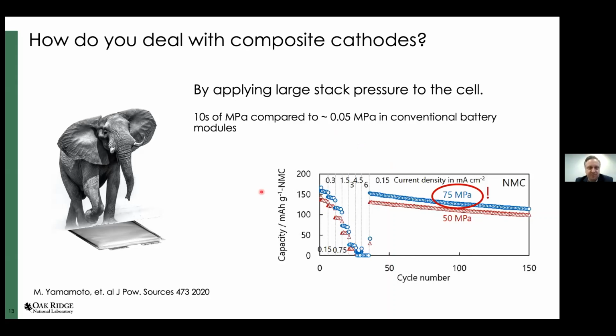Mark, I unmuted you in case you want to add anything. Yeah, no, I'm quite concerned about these pressures, and if you're scaling up and trying to make large pieces, if you have any kind of flaw, are you just going to crack your solid electrolyte? That's one of the things that I'm concerned about. But yeah, those are huge pressures. It's a brute force method of keeping your interfaces together. Yeah, I find it hard to believe that it's a practical solution. No, not at all. We do like to keep cells under pressure in the battery pack, obviously, but it's orders of magnitude less than that. This is very much impractical.